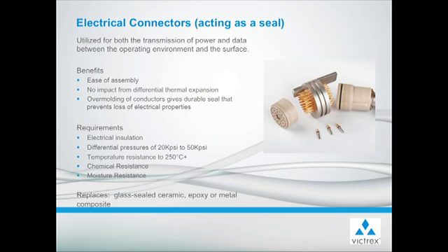Downhole electrical connectors also perform in a sealing capacity. They're utilized for both the transmission of power and data between the operating environment and the surface. The benefits of PEEK include its ease of assembly. There's no impact from differential thermal expansion, which typically results in a loss of electrical insulation in traditional materials, usually caused by the thermal expansion differences and the gap that occurs between the conductor and insulator. The overmolding of PEEK on the conductors gives a durable seal that prevents the loss of electrical properties.